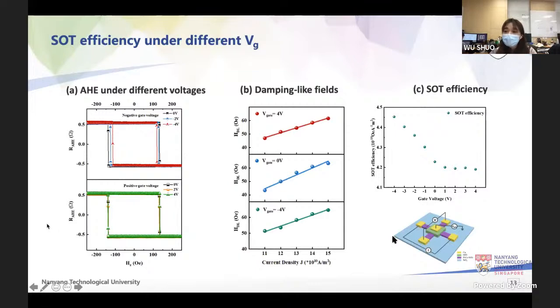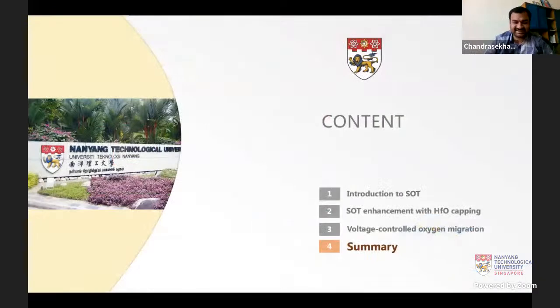Also, based on harmonic measurements, we can get the damping-like field at different gate voltages, and we can get the SOT efficiency. Similar to the AHE measurement, we observe the SOT efficiency gradually decreases, then remains almost unchanged under positive voltage. So we believe that a larger electric field enables more oxygen migration from the HFO layer to the cobalt layer. To investigate further, we think this is enhanced by an interfacial oxidation of the FM layer.